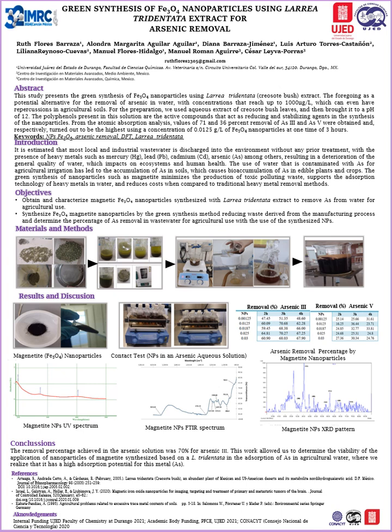The quantification of the concentration of arsenic 5 and 3 in representative solutions of agricultural soils was carried out with contact tests to measure the absorption of arsenic using atomic absorption spectrophotometry equipment with a graphite furnace, a GBC Scientific model, with a collection rate of 9 microliters per second and a sample volume of 30 microliters.